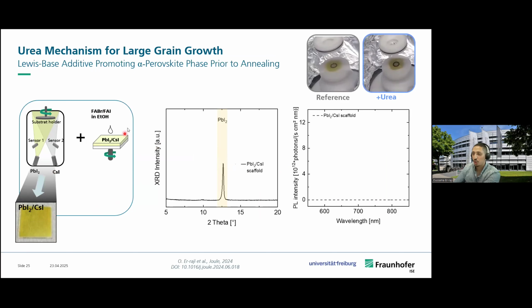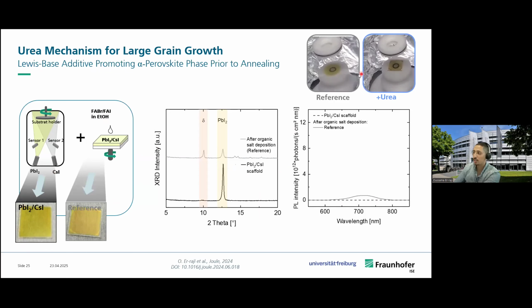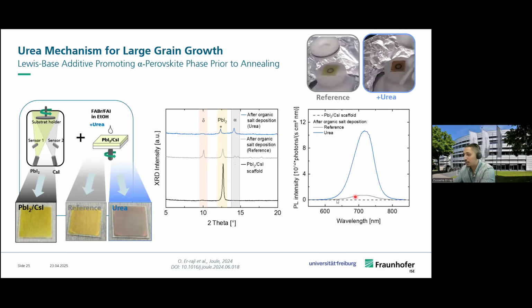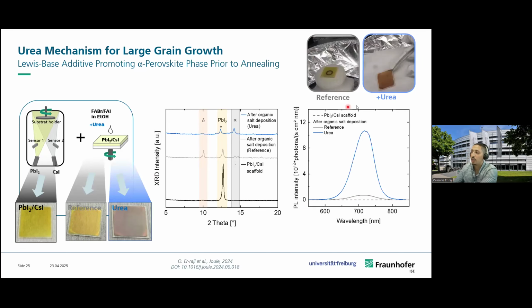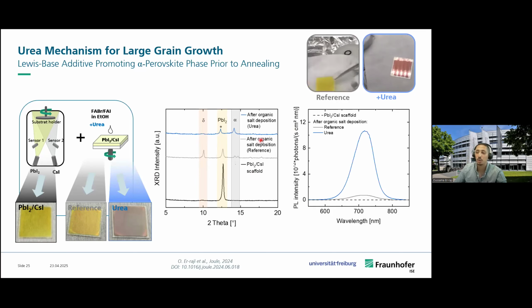Now, if we solution process the reference solution without any urea, you can see this also in real time here in the videos. The color stays yellow. We have a delta perovskite phase that appears, and we have a small photoluminescence response. However, if we spin coat the solution with urea, we already see, as you can see here in the video, that the film becomes brown in color even before going to annealing. And this is reflected in the fact that we don't have any delta perovskite phase, and we have a strong alpha perovskite phase presence prior to the annealing, which is seen through a strong photoluminescence response.